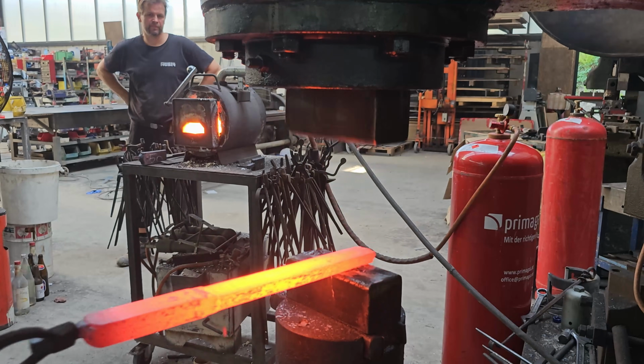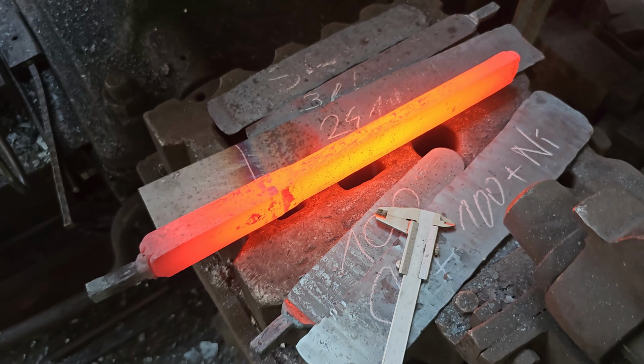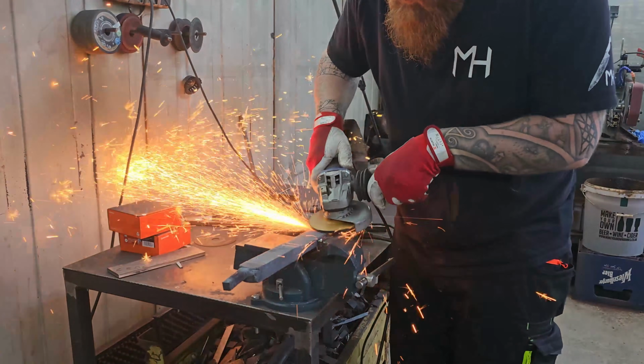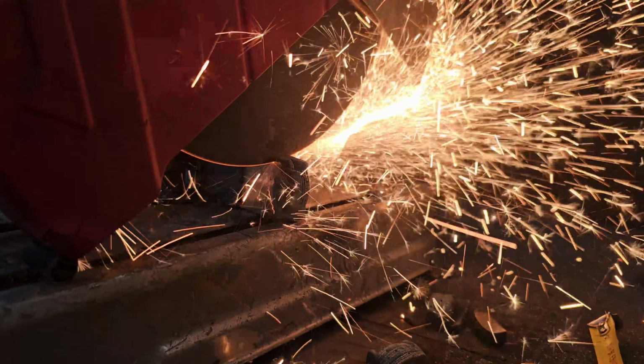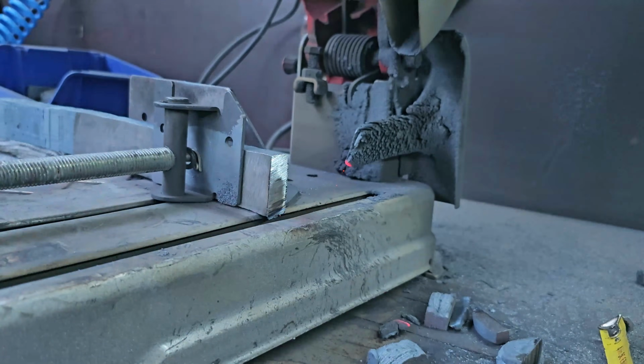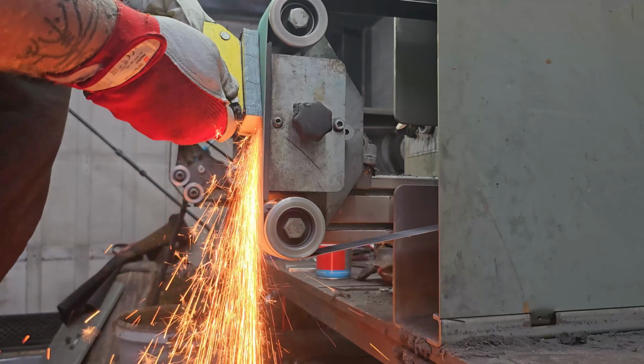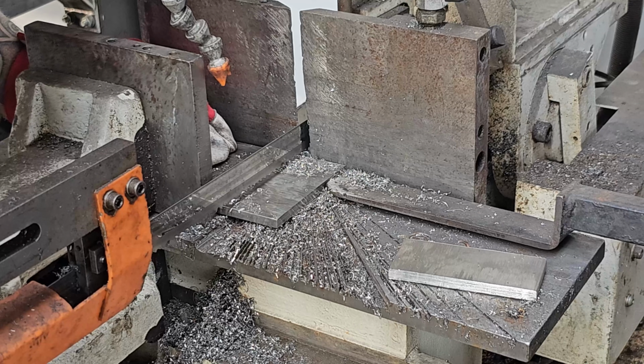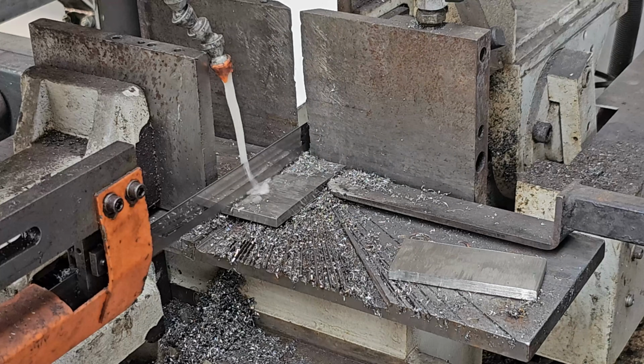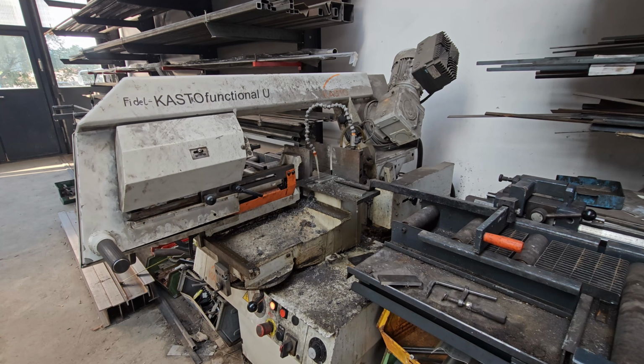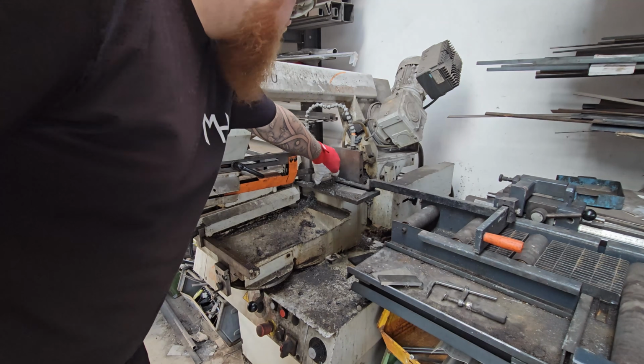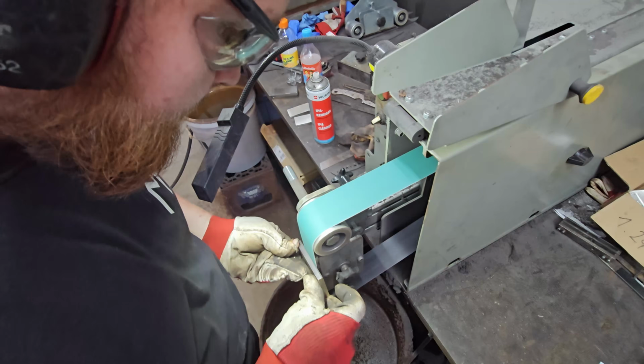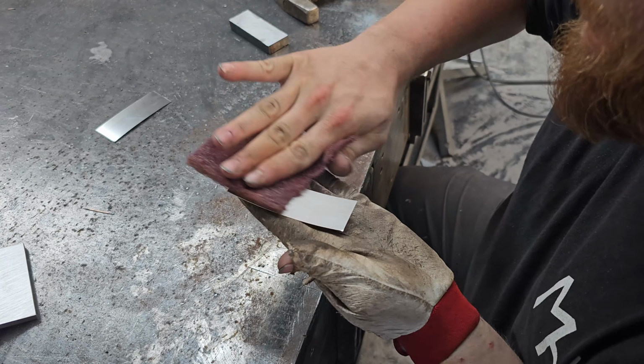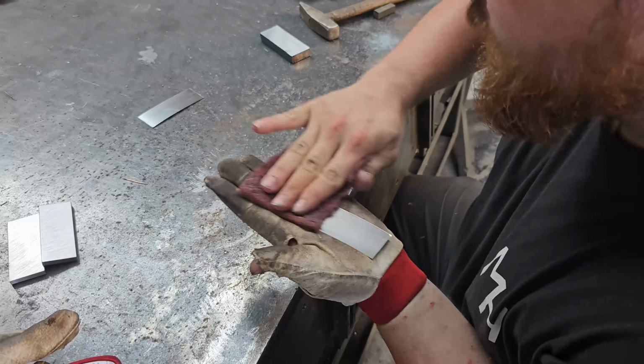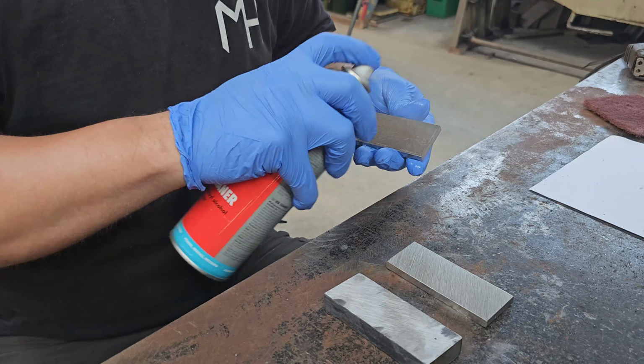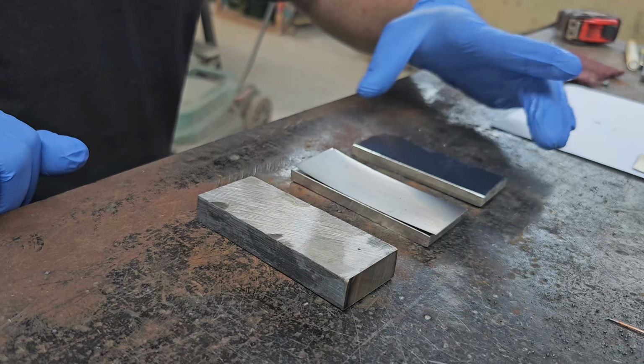I forged a piece of now 109 layer Damascus into a bar of 40mm wide and about 15mm thick in the front. The back I'm going to just cut down, and now we're going to prep the pieces of stainless steel that are going to be the cladding. Yes, you heard correctly, it's going to be a 109 layer core with some stainless steel on the outside, cutting up on the bandsaw. Then put some pure nickel in between the core and the sides, so the carbon from the Damascus is not going out into the outer layers that are soft, and keep where it should be in the core.